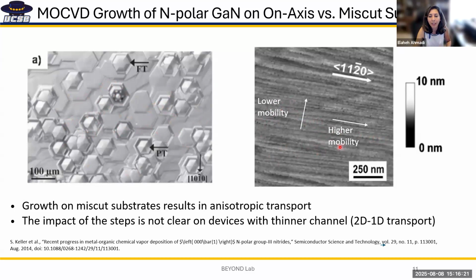But then the thing is that the transport is anisotropic. So parallel to these steps, the mobility is higher, and perpendicular to the steps, mobility is lower. But that's not a problem because we can basically align the devices such that the current transport is aligned with where the electron mobility is higher.